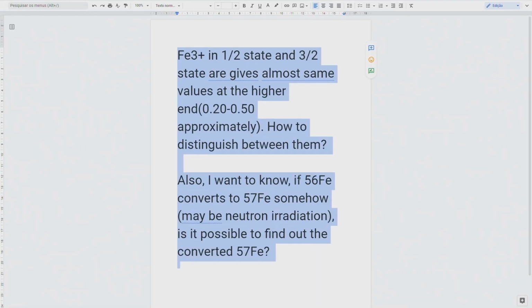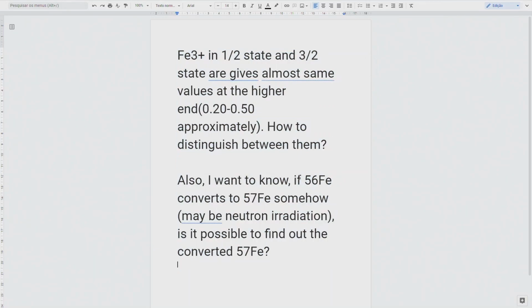To the second question, if I understand well, of course, it's possible when you are irradiating using different techniques, but it depends on the energies. I remember having worked on systems which were irradiated with neutrons. The objective was to modify the valency state and also the position of iron from octahedral to tetrahedral, or vice versa, in the case of garnet. But the energies were too low. It seems to me that you need very strong energies. But I don't know if I replied to this question, or if someone has some comments.